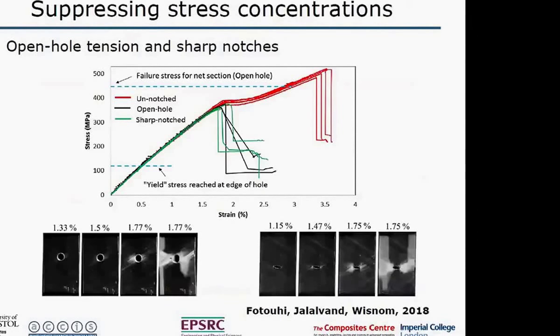One of the whole things about this was to see what happens when you go to a notch response, because the whole thinking about this pseudo-ductile response was that if you've got this ability to redistribute load, then it should be less sensitive to notches than conventional carbon fiber composites, which, if you put a notch in it, a stress raiser, you see a big reduction in static strength. And that's exactly what we see.